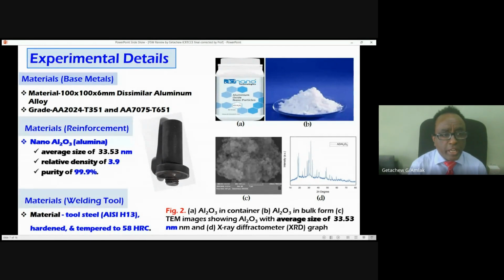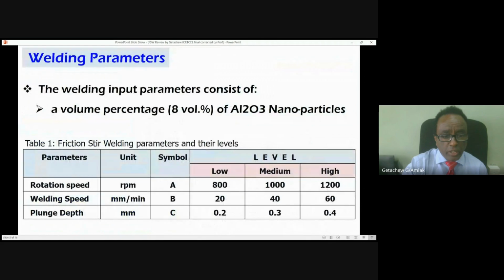For this particular case, reinforcement has been done, and alumina nanoparticles have been used with an average size of 33.53 nanometers, a relative density of 3.9, and a purity of 99.9%. Actually, this is a very critical addition used in this study.